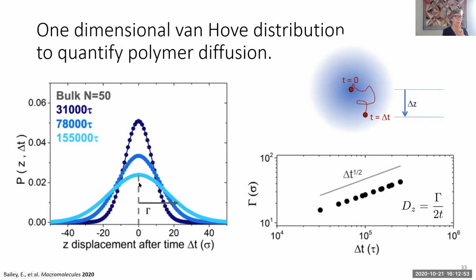So the most probable is that it hasn't moved off of Z equals 0 at all, and it'll be symmetric in both directions because this is the bulk, right? And at longer and longer times, from the dark to the light blue, the distribution just spreads out with time, right? So that makes sense for diffusion in an isotropic polymer melt. And then the width of this distribution function goes as delta T to the half, and we can extract a diffusion coefficient. All right, so that's your reminder of the Van Hove distribution for dynamics.